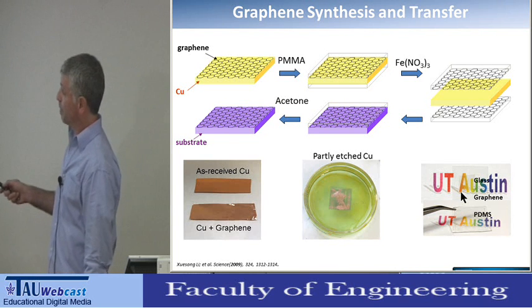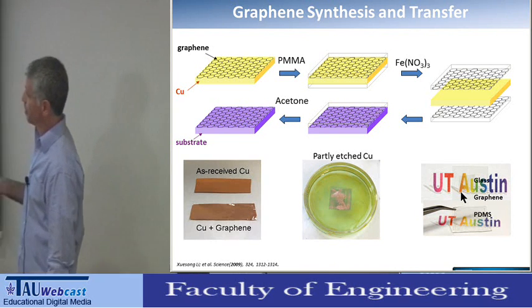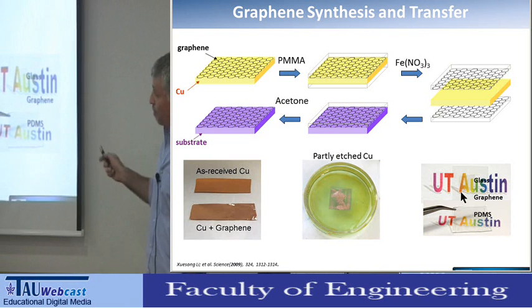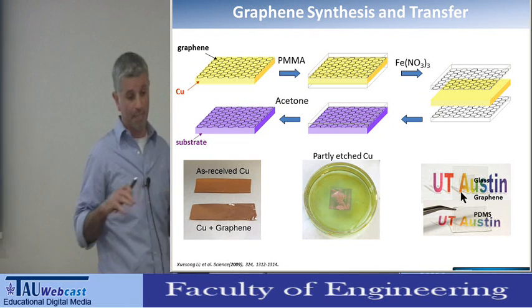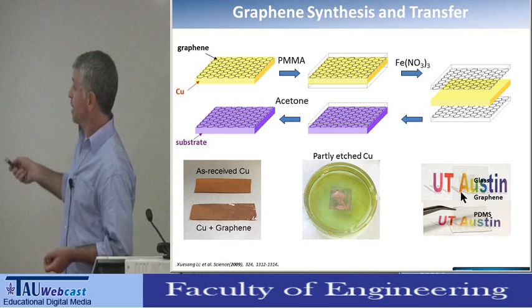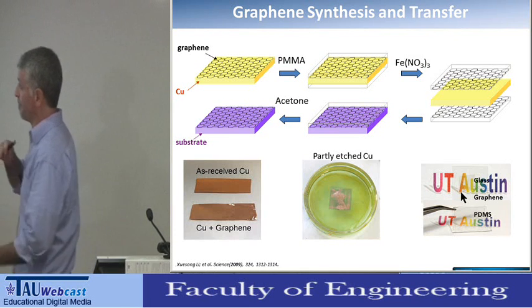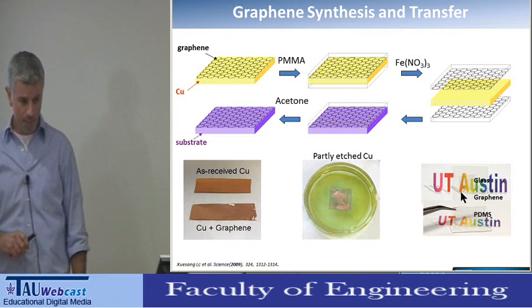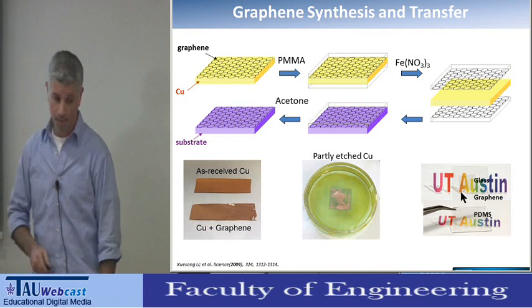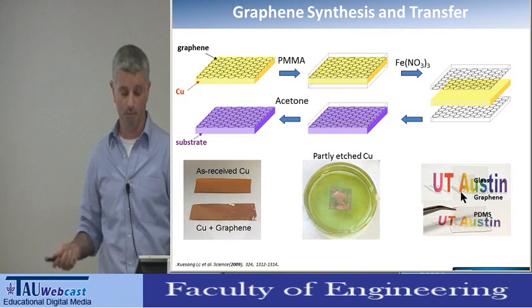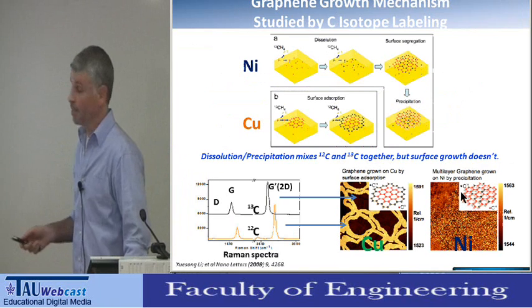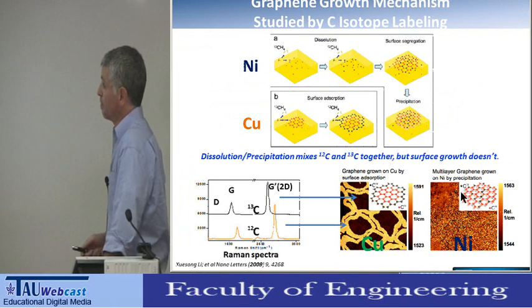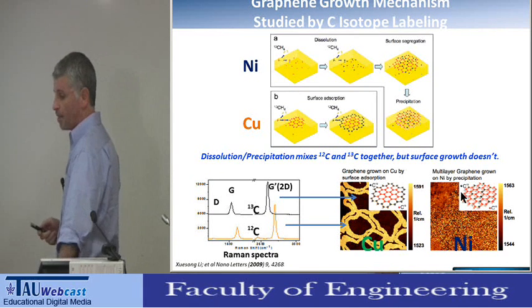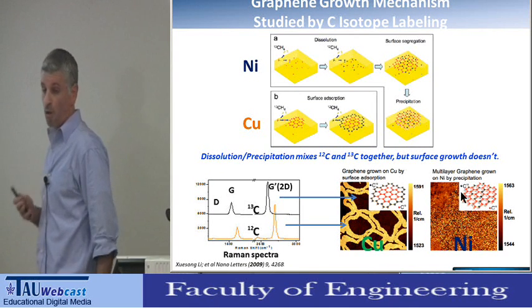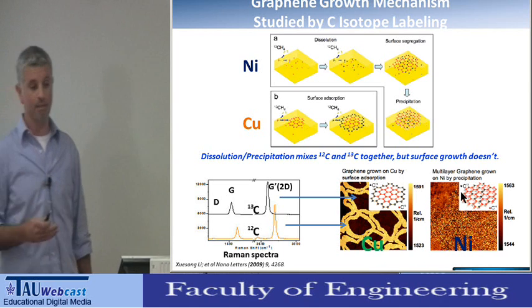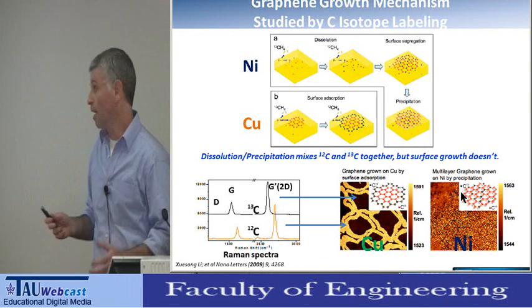Then after the growth, when you have the graphene-coated copper, you spin coat some polymer on it for mechanical support. Then we etch the copper away, transfer the polymer with the graphene on the bottom to the target material, and continue working with the graphene or characterizing it. And so now I will explain why on copper it just works so well and grows as a single layer at such a large scale.